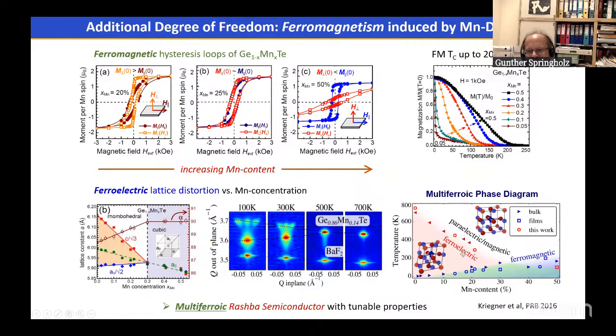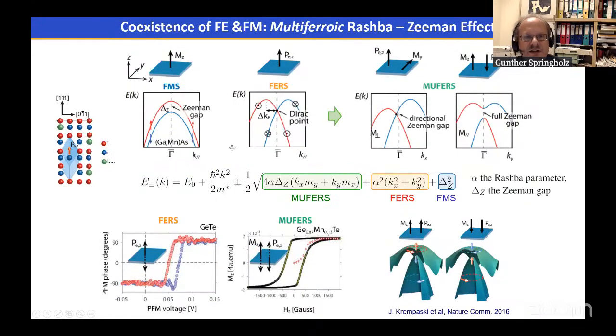So from this, we have constructed a kind of multiferroic phase diagram, where in red here is the region of ferroelectricity, with the symbols indicating the ferroelectric Curie temperature. Here in blue is the ferromagnetic transition temperature measured by SQUID, for instance. And in the green region here, we have a superposition of ferroelectric and ferromagnetic properties, in which the system is multiferroic.